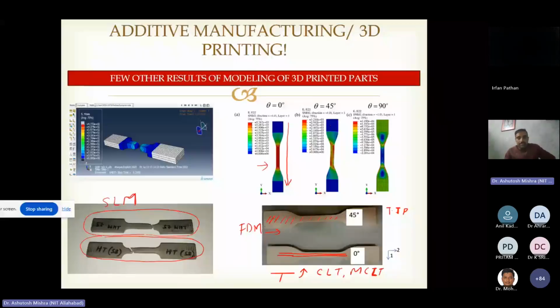Now, while modeling the SLM part, as you can see, there are no lines or rasters visible. This is because the laser which is used produces a very fine product, which, from what I have noticed, has a surface roughness of less than 3 micrometer if it is produced roughly. For a more fine finish, we can get a product of around 1 micrometer surface finish also, that is Ra 1 micrometer. For a tensile specimen, Ra 1 micrometer is okay, but for a fatigue specimen, we require a surface roughness of Ra equal to 0.5 micrometer.